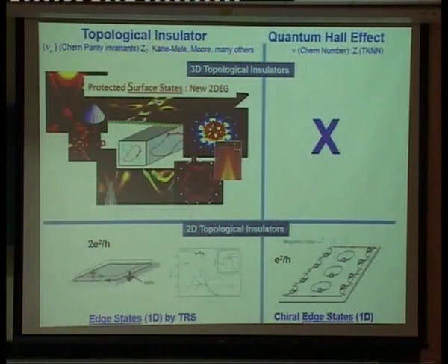So this is exactly what we are probing. In fact, we started out probing these materials through transport, and we moved to spectroscopy partly because of the theory, because the actual topological order, even according to theory, cannot be probed through transport. Because the surface transport of a 3D topological insulator is not Z2 topologically quantized. Joel touched on that point.